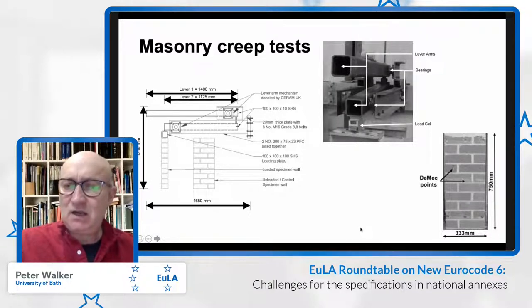To measure the displacement, rather than using LVDTs, because of the long-term nature, we used a more traditional approach, if you like, of using demountable mechanical or DEMEC strain gauges, in which these stainless steel pointers are glued to the surface of the masonry on both sides. We measured the movement incrementally over time during the period of the creep testing.